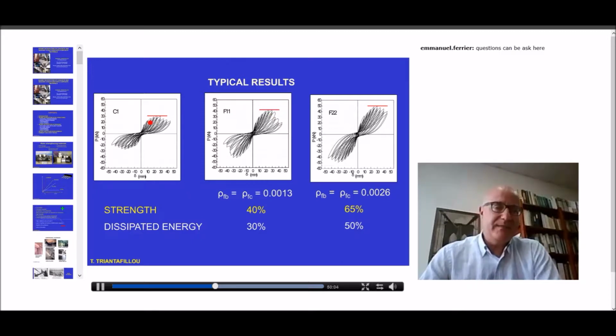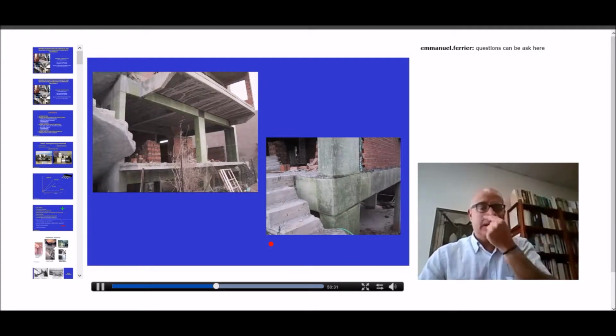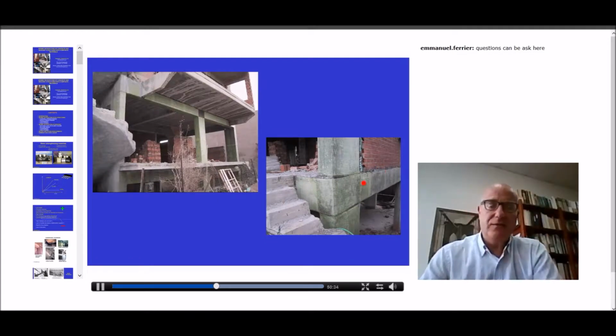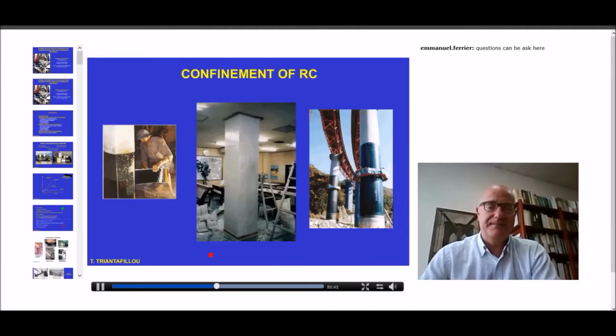The response of the same joint, of an identical one, if we use a single layer of a given material, one layer of a low thickness carbon fabric, and that's where we go if we use a couple of layers. So there is a substantial increase in strength, 40% for one layer, 65% for 2 layers, etc. And also there is increase in the dissipated energy. And a couple of photos on how those fibers are applied. We have both horizontally placed as well as vertically placed fibers in the joint area.